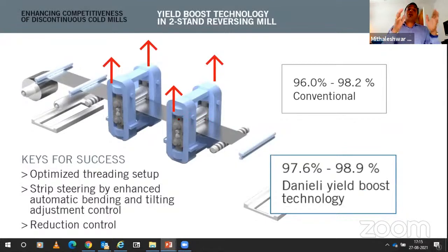So the length remains the same, but the thickness of the material gets reduced, and that effect is something we can see here. For the conventional two-stand rolling mill, it was 96 to 98.2%. After implementing the yield boost technology, we achieved the overall material yield for the mill of 97.6 to 98.9, up to 99 also. Very challenging, but depending on the product mix and the strip dimension, it is achievable, and we have made it.